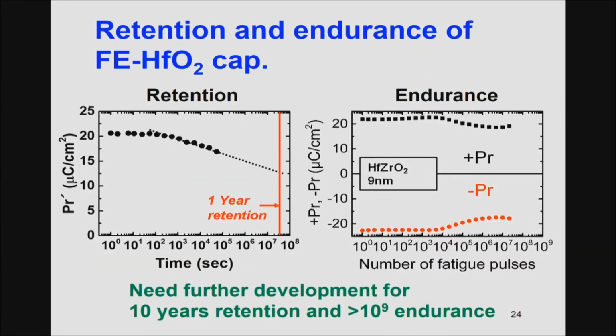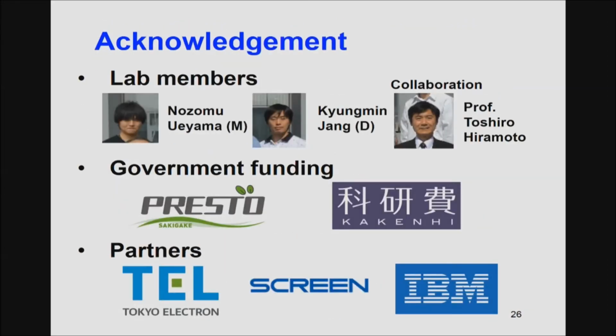Let me touch a little bit on the reliability. Here is the retention, and here are the endurance characteristics of the ferroelectric capacitor. From our capacitor results, I expect more than 1 year retention and also 10 to the 8th endurance cycles. But of course, for practical use, we need to guarantee 10 years retention. For the endurance, the requirement may be mitigated for this kind of architecture, as I mentioned before. For example, if we power off and power on this NVSRAM every 1 millisecond, we probably just need 10 to the 9th endurance cycles. But anyhow, we will need further development for the 10 years retention and such reliability requirements.